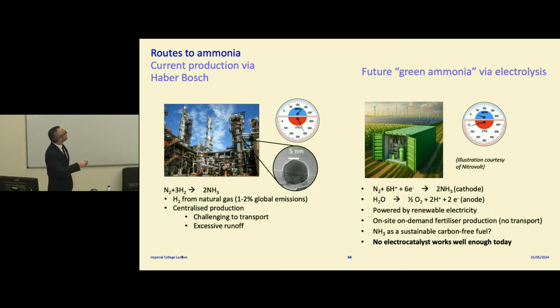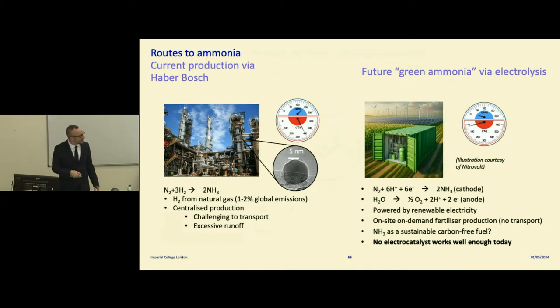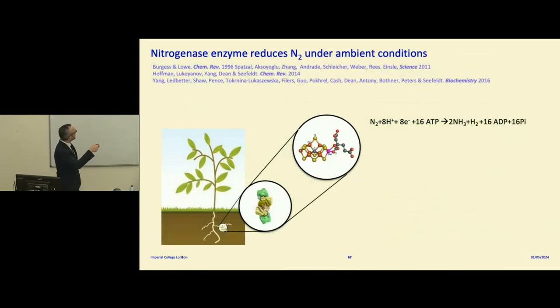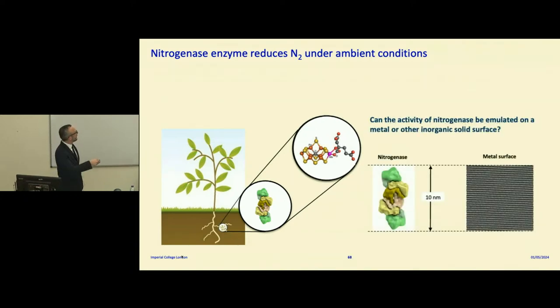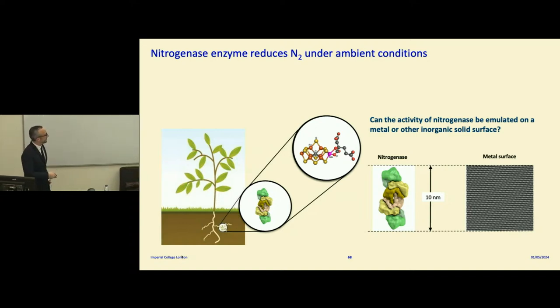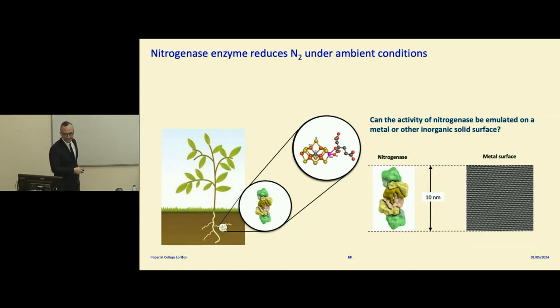But to get that to work, you need the right catalyst, and no electrocatalyst works well enough today. Because, as already mentioned, the nitrogenase enzyme can do it under ambient conditions. The thing about nitrogenase is that each catalyst has a huge footprint, and you can pack a lot more active sites onto a metal surface. Each dot here is an individual metal atom, so you can get much higher rates if you were to use a metal surface instead.